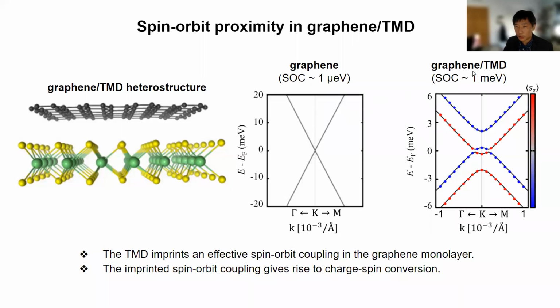Because of the large spin orbit coupling of the TMD, it results in a proximal SOC on the graphene. So the band structure of graphene would then be modified from this linear dispersion to this spin split dispersion. The energy scale here is much smaller, in milli electron volts. So we are talking about effects that are probably only visible at low temperature, but this is a study where we want to understand more of the fundamental physics.